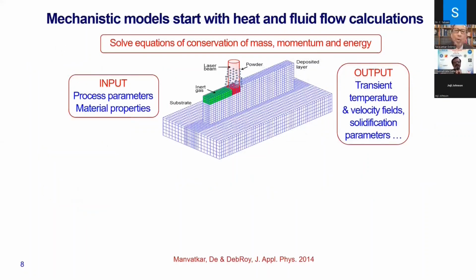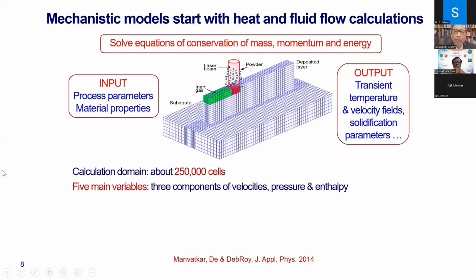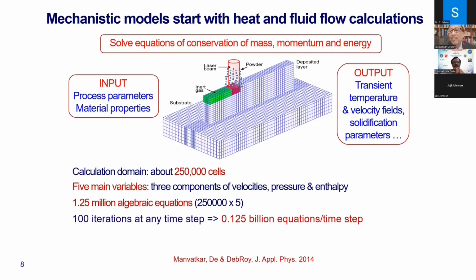What we do in mechanistic modeling is shown here. We start with heat transfer because that dictates cooling rates and also the microstructures and properties and ultimately the performance of the parts. So what we do is we subdivide the domain into many cells, like in this case 250,000 cells. We solve for velocities, pressures, and enthalpy, 5 variables. We linearize them. At the end, we have a little more than 1,000,000 algebraic equations. We do iterations to solve these problems. So 100 iterations at any time step is about 1/8 of a billion equations. With 1,000 time steps, we are solving 125 billion total equations.